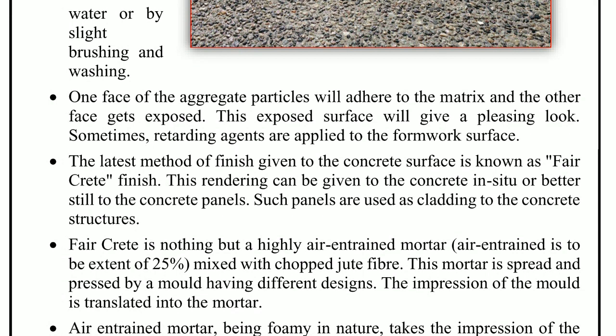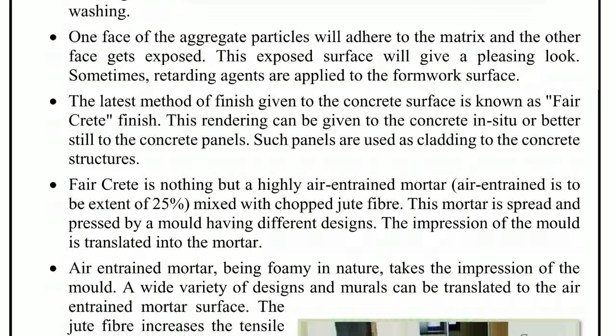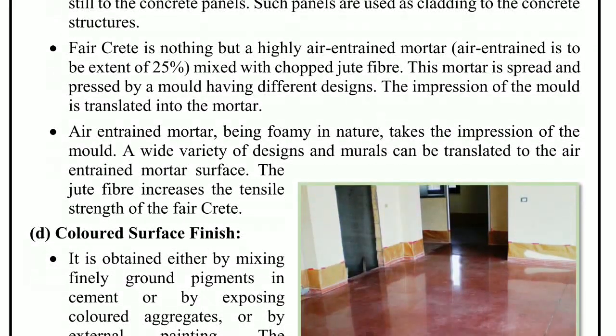After washing, one face of the aggregate particle adheres to the matrix and the other face gets exposed, giving the surface a pleasing look. The latest method of finish given to concrete surface is known as fair-crete finish. This rendering can be given to concrete in-situ or to concrete panels used as cladding to concrete structures. Fair-crete is nothing but highly air-entrained mortar, with air entrainment extended to a maximum of 25%.